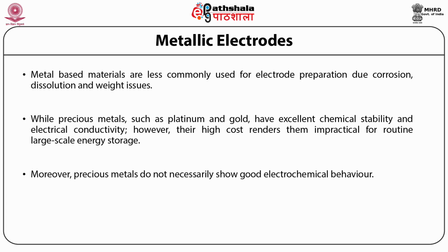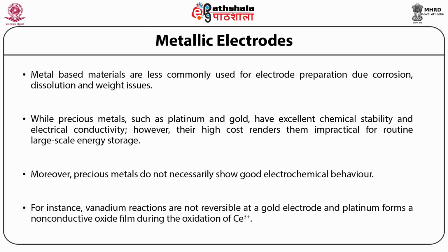Moreover, precious metals do not necessarily show good electrochemical behavior. For instance, vanadium reactions are not reversible at a gold electrode, and platinum forms a non-conductive oxide film during the oxidation of cerium 3+.